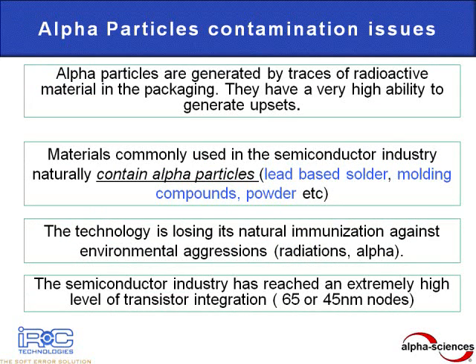Thorium and uranium are found naturally in many of the components used to manufacture semiconductor devices, such as packaging materials, molding compounds, and lead-based solders. As such, many of these materials contain certain levels of alpha emission. Even lead-free solders are testing high in alpha content. The higher the alpha content of the material, the greater the chance of induced soft errors. And with today's increasing level of transistor density integration comes an exponentially increased sensitivity to soft error.